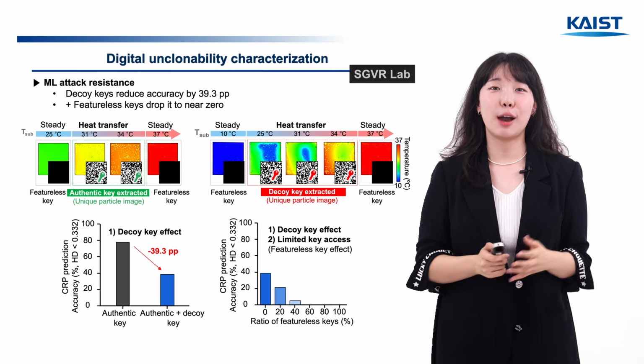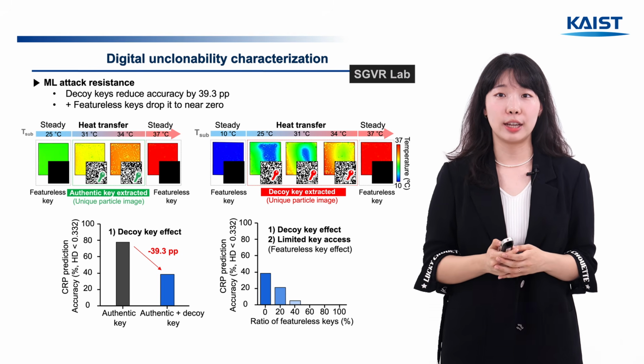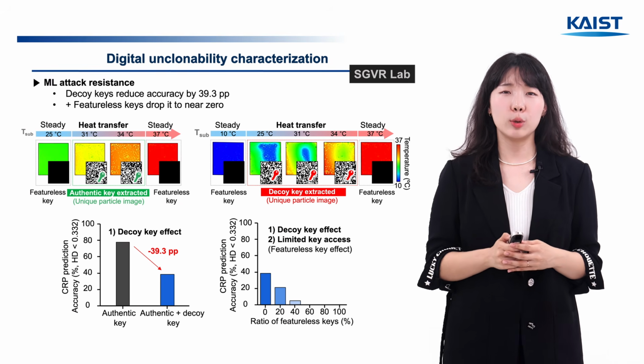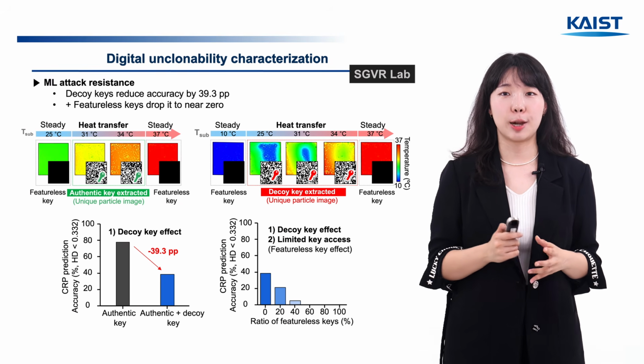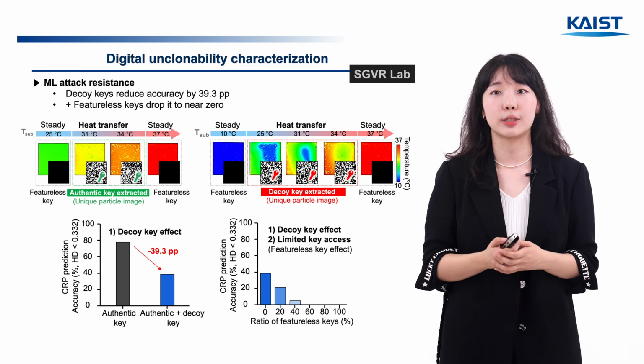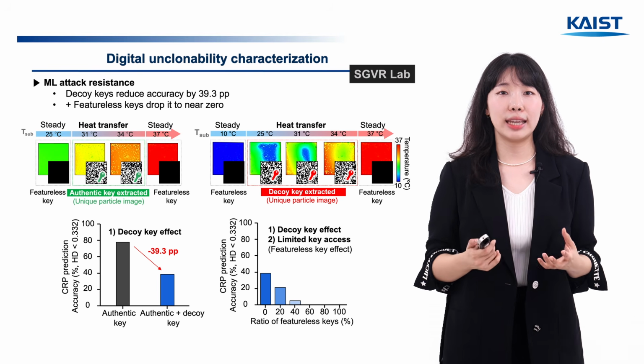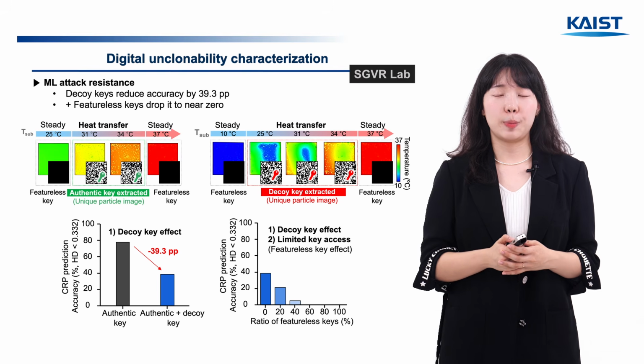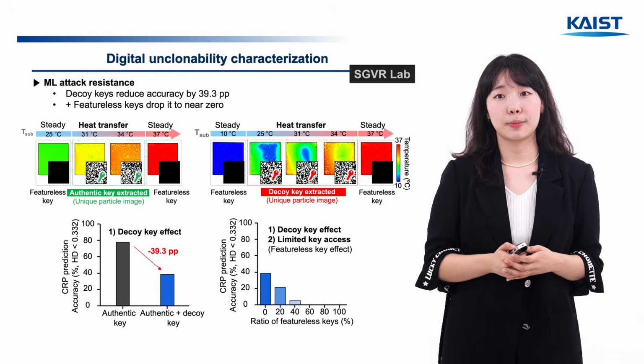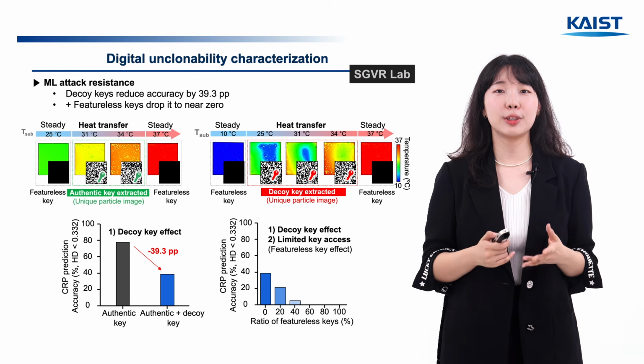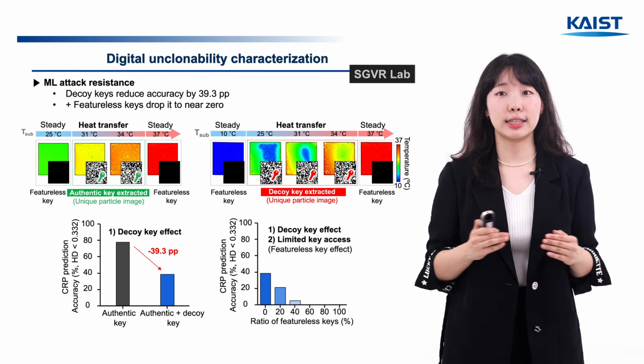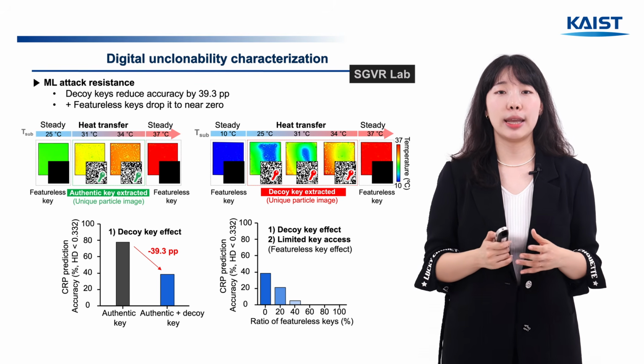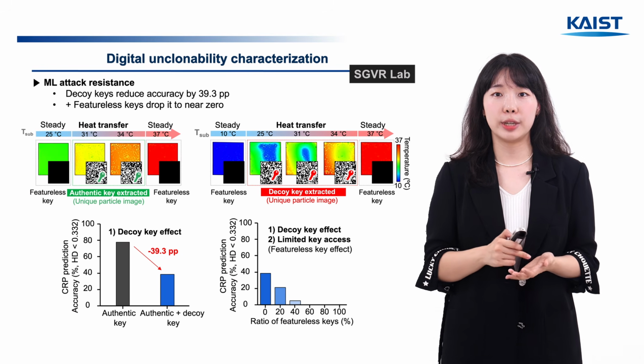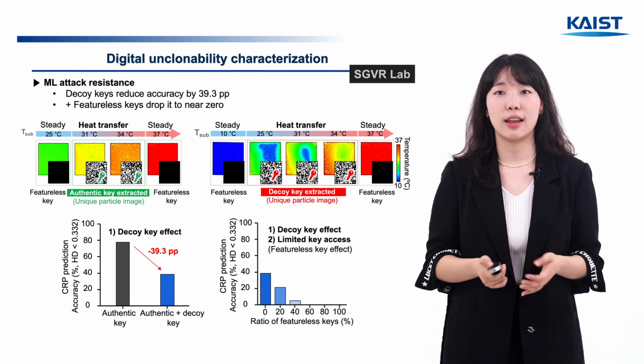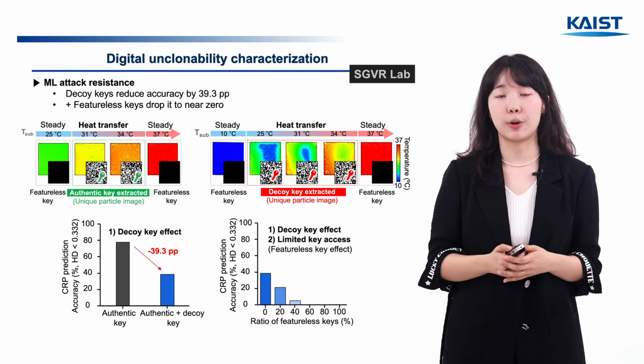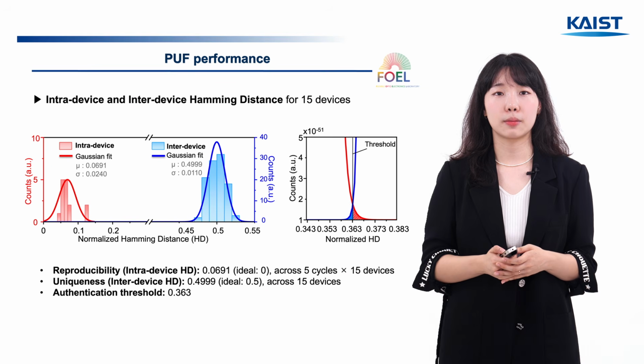We evaluated how effectively these two methods defend against machine learning attacks. A model trained on the real key reached a CRP prediction accuracy of around 80%. When the disguised fake keys were added, the accuracy dropped by around 40 percentage points. And when we mixed in the featureless keys that form during the constant temperature periods, these keys made up over 40%, bringing the prediction accuracy below 5%. You can find the machine learning details on our GitHub, linked in the paper.